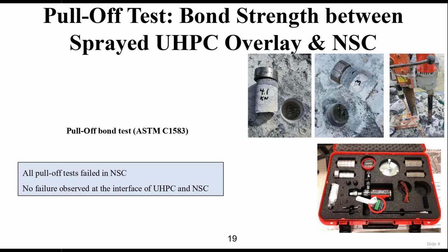But it's good enough. We didn't do that in the case of the Virginia DOT, and that was one of the SAM concerns. In that case, I just didn't want to do it because it was the first time that we were applying this. But later, we've done some work, and when we applied the UHPC without any steel fibers, you can smooth the surface, but it's not going to be as smooth as if you apply plaster.